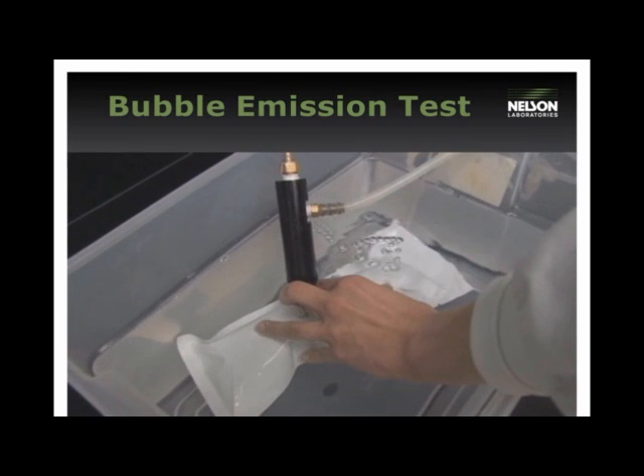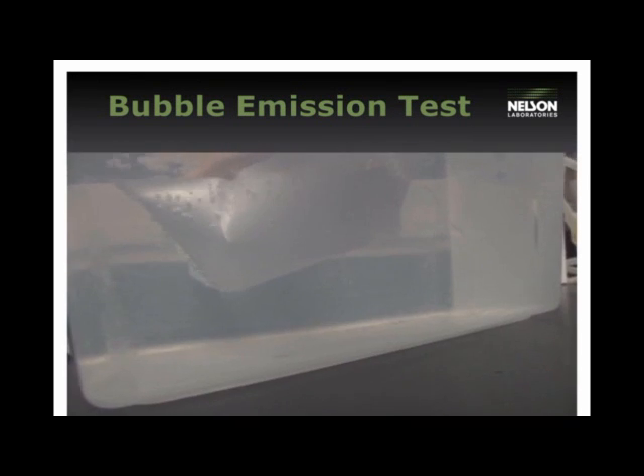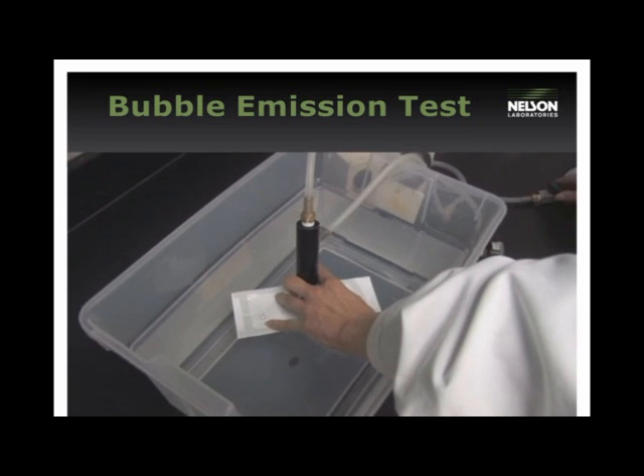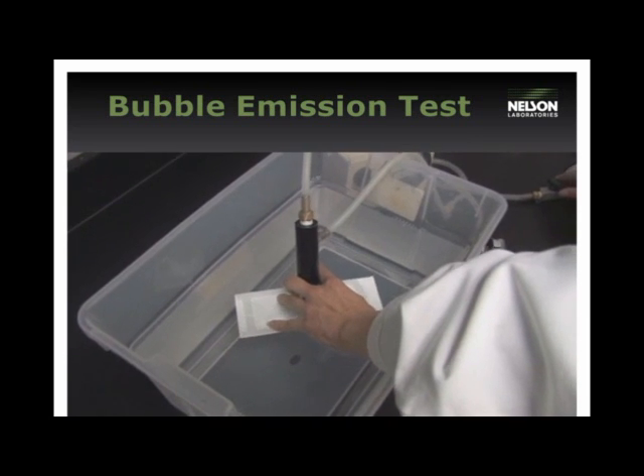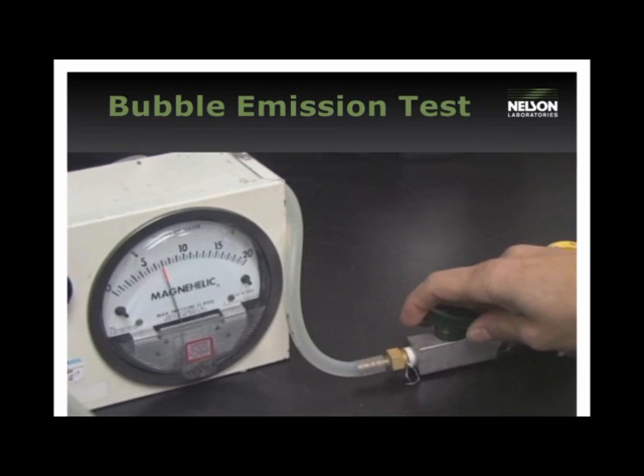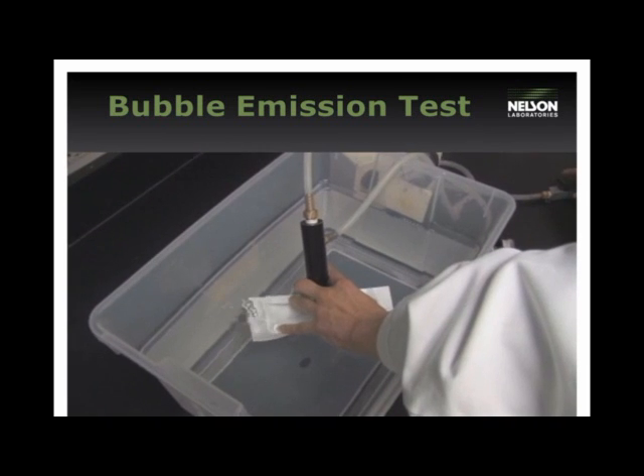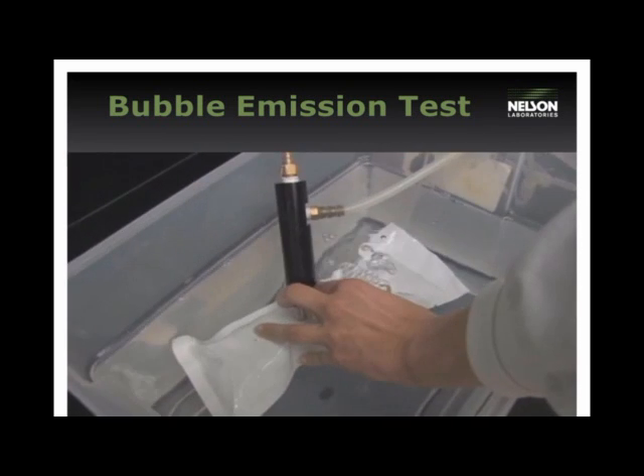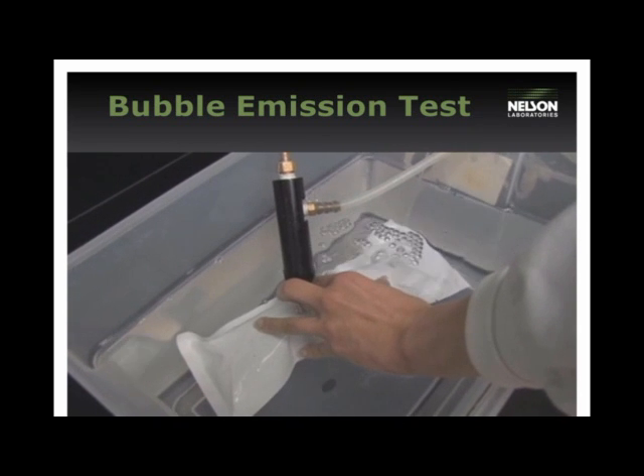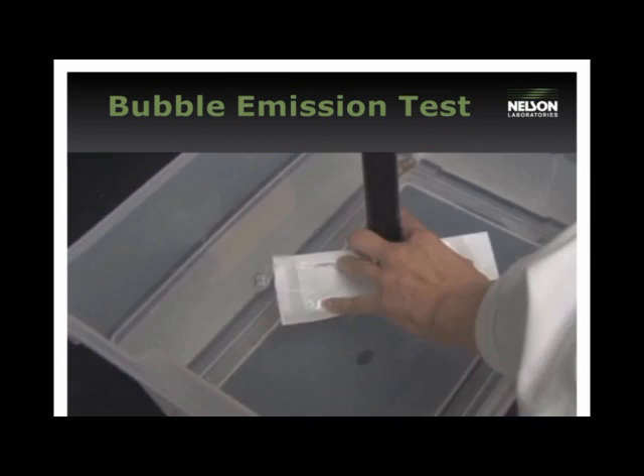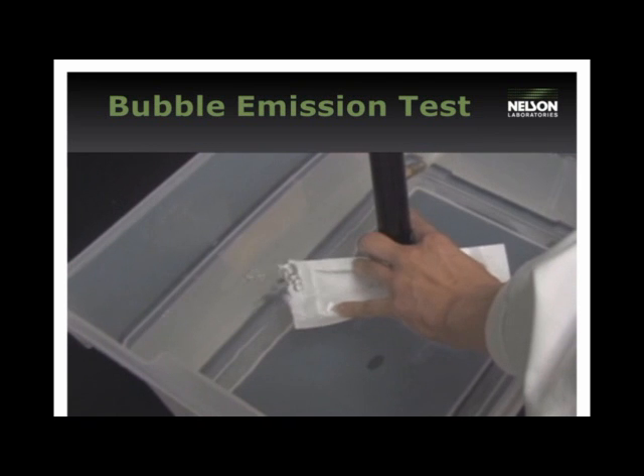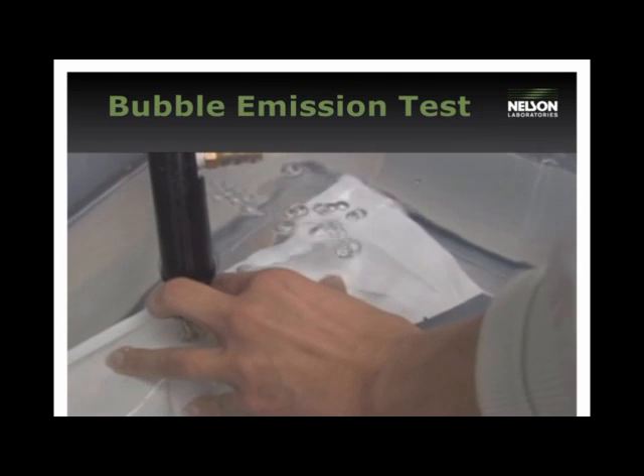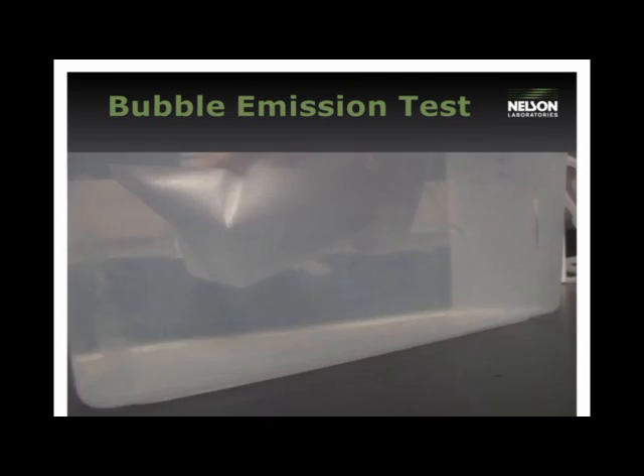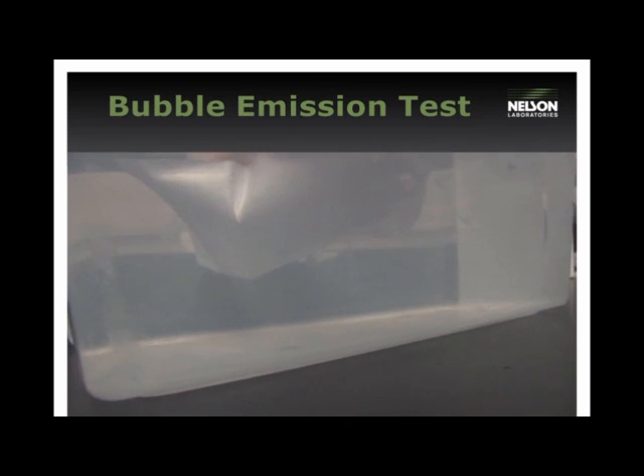Bubble emission is a whole package integrity test. This test detects leaks in both the package and the seals. The sample is submerged in a bubble fluid and inflated to a set pressure. The package is visually examined for bubbles. Any leaks will be seen as a steady stream of bubbles coming from a fixed point. Here is a leak in a seal. This is an example of a hole in a package.